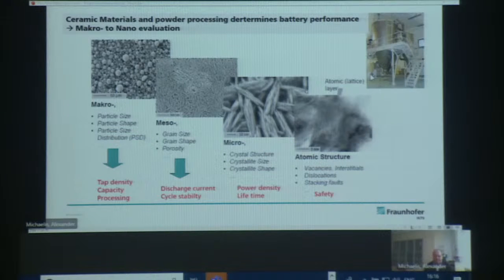Why is this a subject for ceramics people and not only for chemists? This is briefly illustrated on this slide here. You see here, it's very important to customize the morphology of your battery powder. Here, lithium cobalt oxide is shown. And you see very advantageous for battery applications is this spherical morphology. And it's good to have big spheres and smaller spheres because this gives high packing densities. You get a lot of this material in a certain volume.